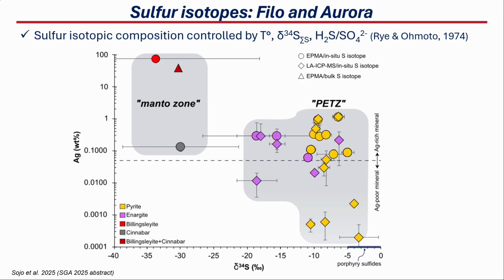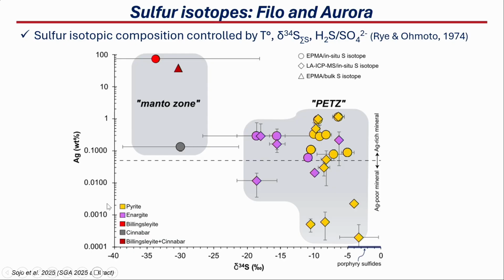But more important, to really understand the physicochemical conditions, we have done sulfur isotopes. And this might be a little bit complex to follow, but essentially sulfur isotopic compositions and the fractionation depend on temperature. So if we have less temperature, fractionation will increase. It also depends on the initial source of sulfur of the system. So it's like how much sulfur we started from, and the ratio between the reduced and oxidized species in the system. So overall, in this diagram, I would like to show the delta 34S. That's how we essentially measure sulfur isotopes. And in this case, I added silver on the y-axis. We can do that for copper or gold. I just took silver, because we actually can see different trends.